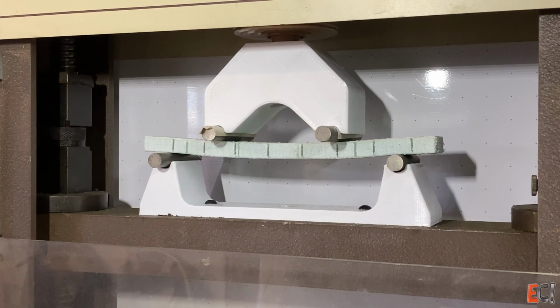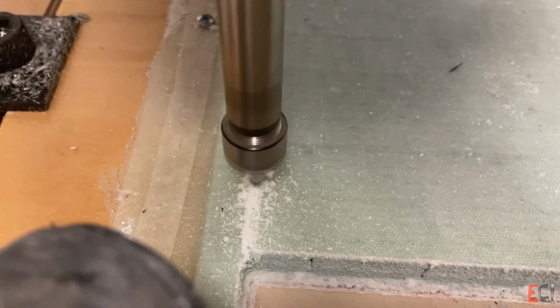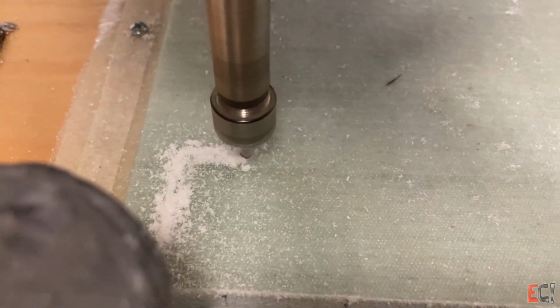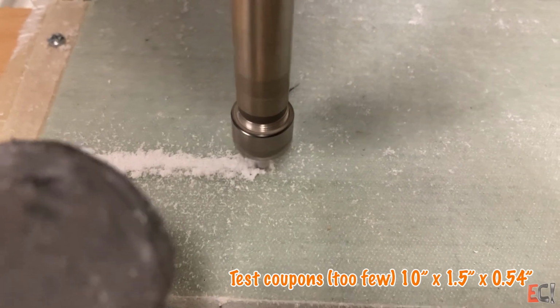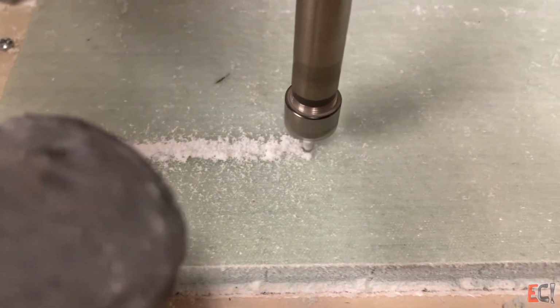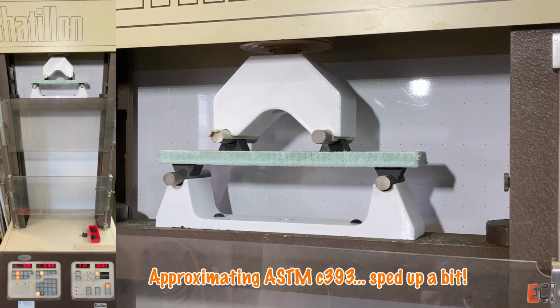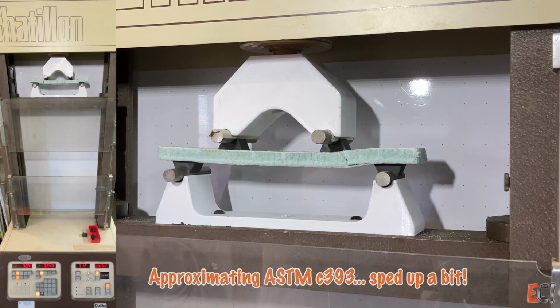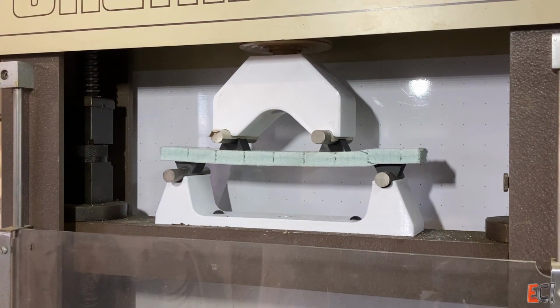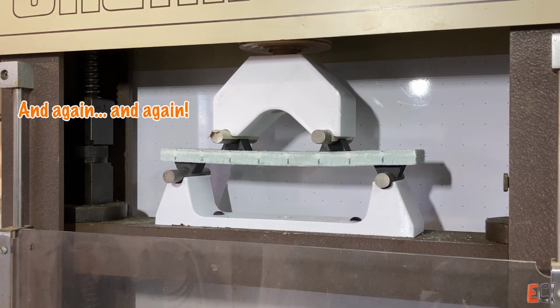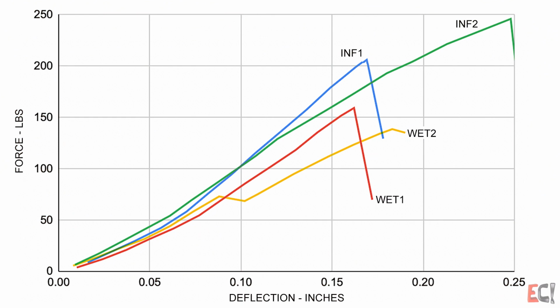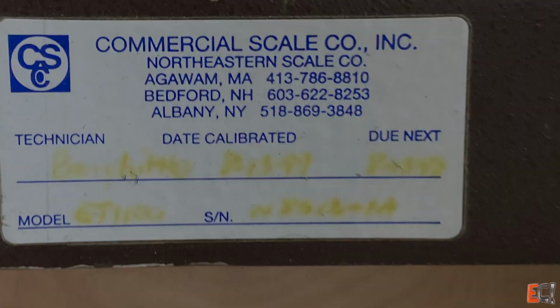So I figured I'd try doing a little bit of testing to see if I could get any data that would show a difference in the core shear properties of the infused versus the wet laid, the ones that have resin filling all the kerfs versus air filling all the kerfs. So I machined out some not enough coupons from the offcuts, and doing my best quick and dirty ASTM C393 impression, I was able to record the data of various points of deflection pressure and plot them on a chart showing two infused samples and two wet laid samples. The infused samples seemed to hold up longer and take more pressure to deflect. But take this for what it is. This machine was last calibrated in 1998, and I don't know what I'm doing.